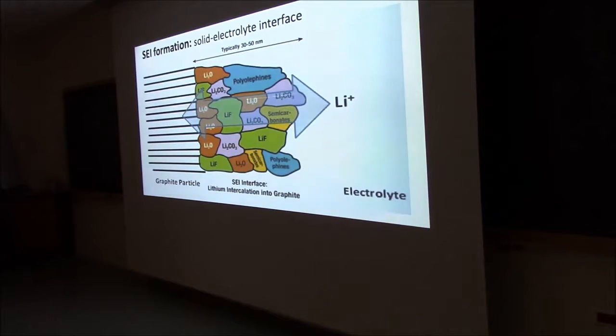But it also limits the lithium transport. So it becomes constant, so you can use it, but if you could get rid of this, everything would be better. So people look into what kind of coatings they can put on top of the graphite to prevent this from happening. This is the so-called solid electrolyte interface. SEI formation, that's the abbreviation they use. A similar thing is happening on the other side, the cathode side, where people do research.